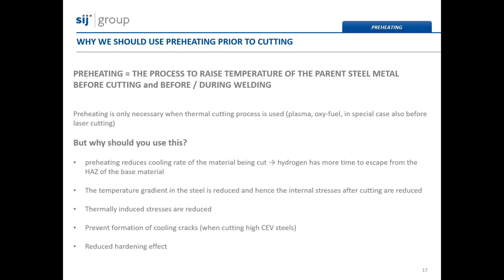The fourth one: if we want to thermally cut high carbon equivalent value grades with high thickness, in order to avoid cooling cracks, we should take preheating into serious consideration. It does not mean that those grades cannot be cut by thermal cutting, but I just want to tell you that we have to follow instructions given by the producer of the plate. And the last reason maybe is that with preheating, we also reduce the hardening effect in the heat-affected zone due to the reduced cooling rates.